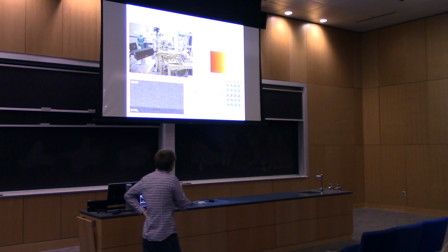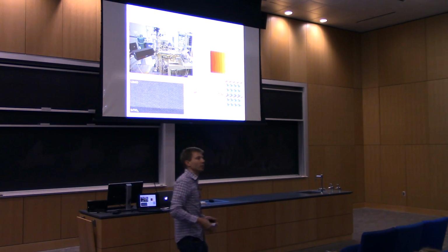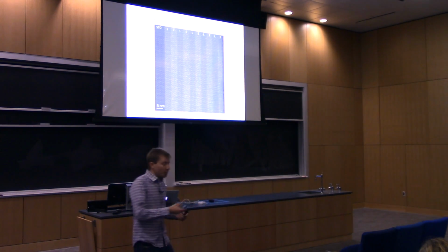We can make sort of metastable cation orderings where we have 2 unit cells of, in this case, these are ferrites. We can deposit 1 unit cell of A-site cations and then 2. And we actually see those in the X-ray. So we have this nominal unit cell control of our growth. Okay, so these are the superlattices.